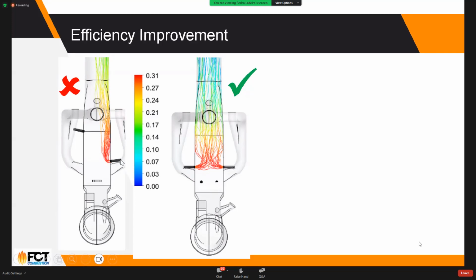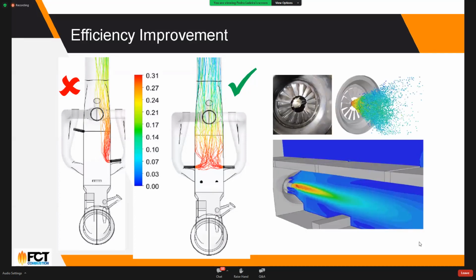The other thing you can do is have a look at your calciner and see if you're injecting fuel only on one side. You put together a CFD model, which is something that we do also, and you see that the fuel distribution is uneven, so you have high oxygen, low oxygen, poor combustion. You can have an even distribution of fuels by injecting at 2 different points, or 3, 4 different points. You can get better results, earlier heat exchange, and then lower temperatures at the preheater exit, which means lower heat consumption, which in turn means a reduction in CO2 emissions. And then you have all sorts of possible distributions and patterns, and the way you regulate flows and how you swirl the flows to get a good and proper combustion.